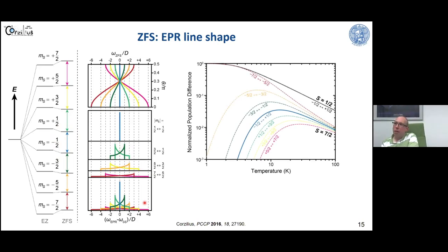One point to consider here also is that if we look at the spin polarization, or the spin populations, of course we have to consider the Boltzmann factor. And at low temperature, that means that all the populations will be condensing here in the lowest energy state, if the thermal excitation is not sufficient to populate practically all the states equally.